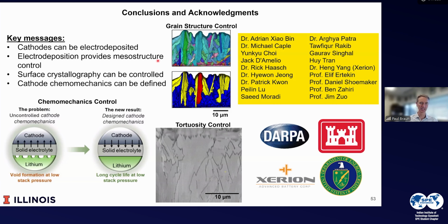And here's just a picture showing the crystallographic orientation, the EBSD. Below that is a map of the sizes. So there's a lot of data that we can extract from this. And then finally, showing the tortuosity that is much reduced in the system compared to a slurry. Just want to point out a few people that contributed extensively to the work here.